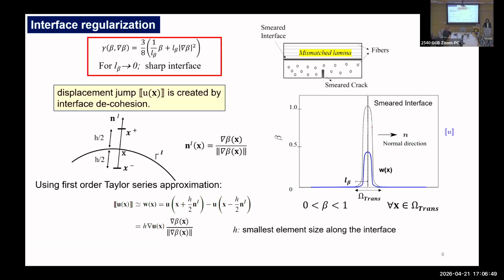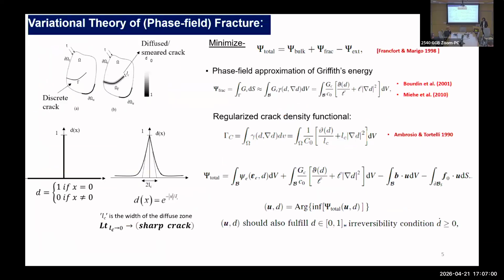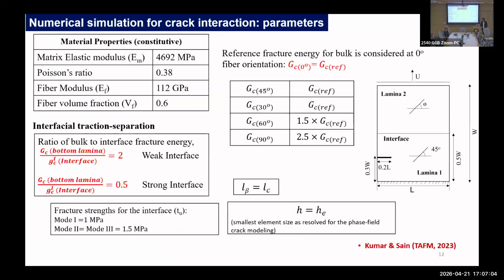I see. And the volume fraction you're interested in is 0.6. That was the volume fraction reported, which one? Oh, okay, in the constitutive description. Somewhere in the table, yes. For this one, I think it was just our parametric study, because if I remember correctly, Tony's paper had a little higher volume fraction. I don't exactly remember the data. But for the first part of the model, you can actually choose the volume fraction for your actual sample. If you know the volume fraction of the fiber, you can calibrate that, because our free energy is expressed in terms of volume fraction, so it's a parameter in the model. I see. Okay, thank you.